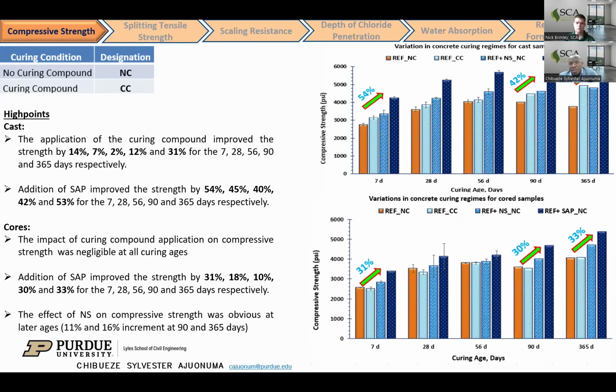We found that the incorporation of the curing compound slightly affected the compressive strength, especially for the samples that were left in the field. The plots above were those cured in the lab, and the ones below were those extracted from the field. So the curing compound had a slight effect on the compressive strength, but we also noticed a consistent increase in compressive strength when we compared the reference mix without the curing compound with those with the addition of SAP.